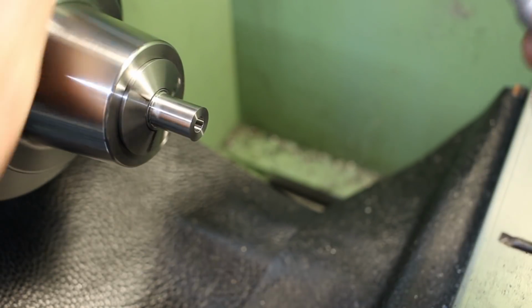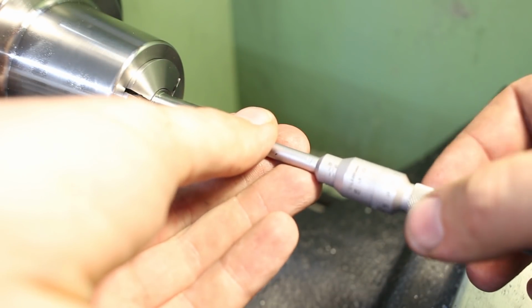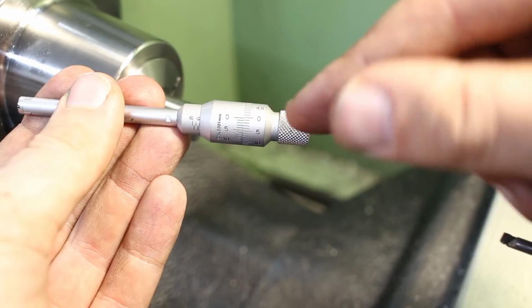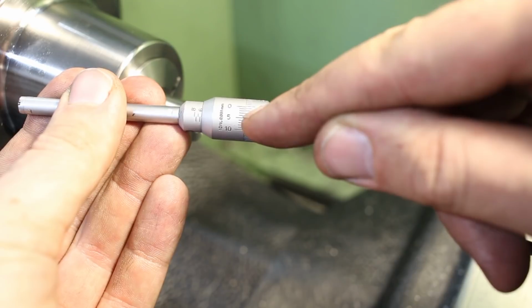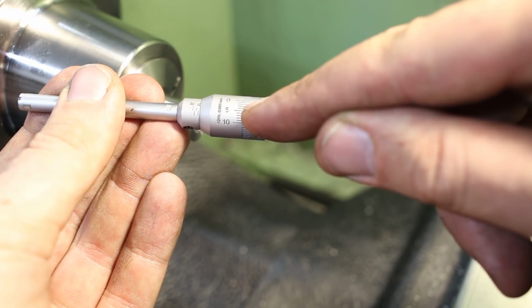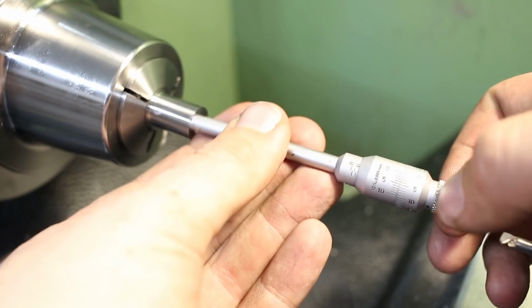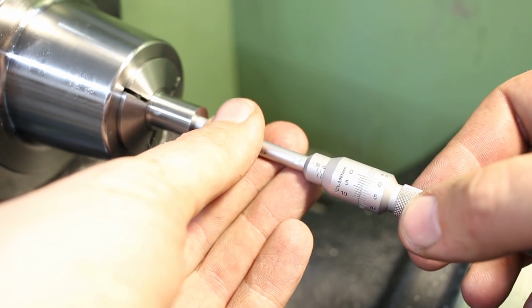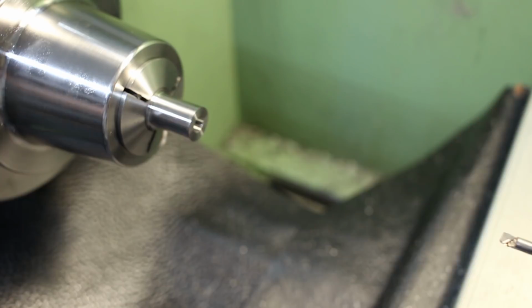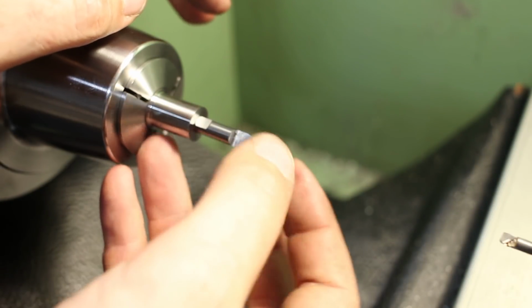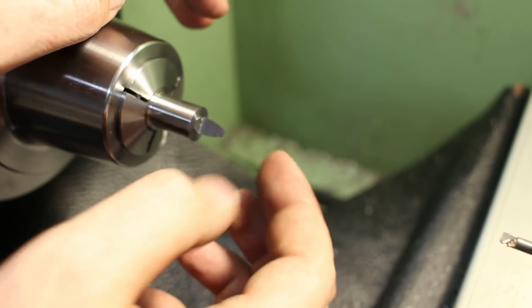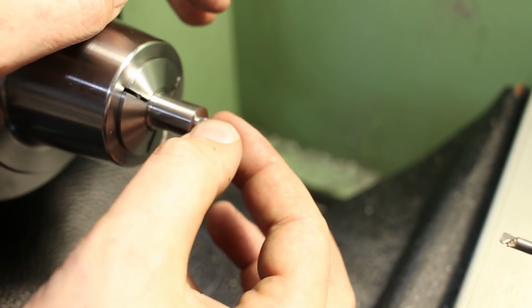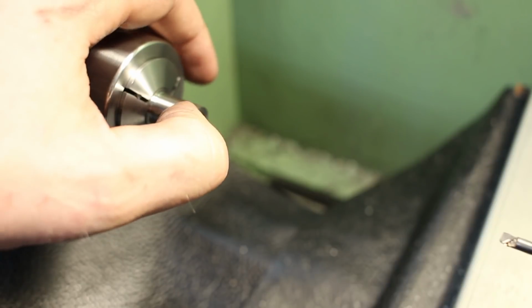Okay, took me a few passes to sneak up on the final dimension, but I hit it pretty darn good. A tiny amount, about 3 to 4 microns oversize to 6 millimeters. I don't have a 6 millimeter gauge pin here, but I have a 6 millimeter carbide shank, which is 5.99, so 10 microns undersize. That's a nice sliding fit. So now we need to cut a relatively precise chamfer.